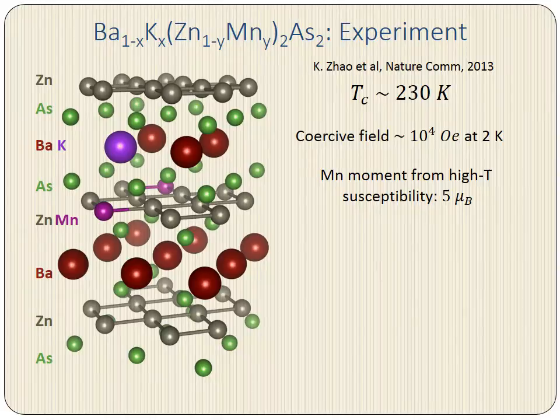Let's review the experimental situation for manganese and potassium-doped barium zinc arsenic, which was first studied and reviewed by Zhao et al. in the following Nature Communications paper. This material has a Curie temperature of 230 Kelvin under optimal doping, which is already higher than the maximum of 190 Kelvin attained in manganese-doped gallium arsenide. The coercive field is also 10 to the 4th Oersted at 2 Kelvin, which we should note is 2 orders of magnitude higher than manganese-doped gallium arsenide. Finally, high-temperature susceptibility measurements indicate effective moments of 5 Bohr magnetons per manganese, which indicates that the manganese ion is in the 2+ charged state.